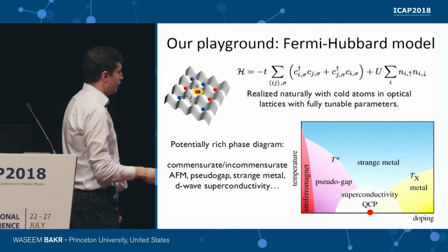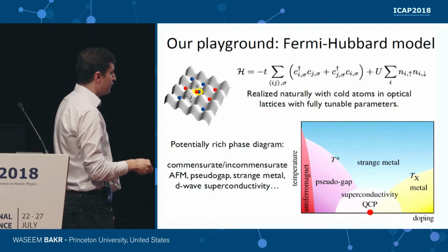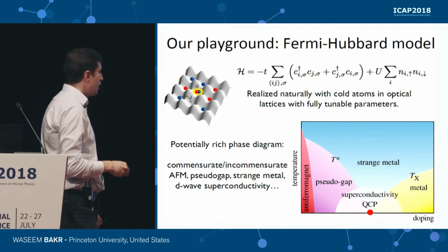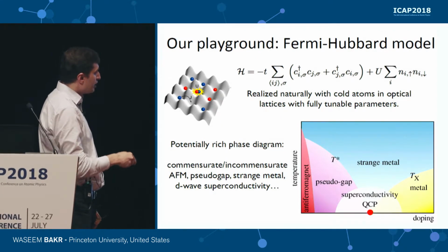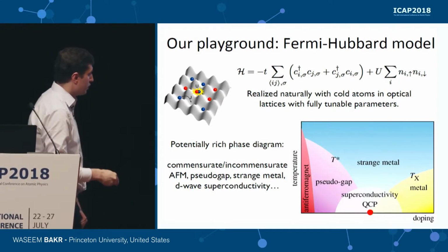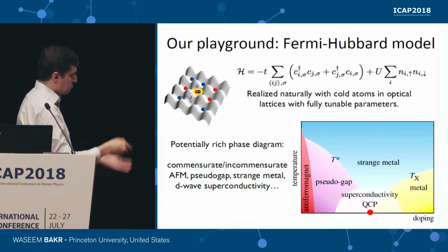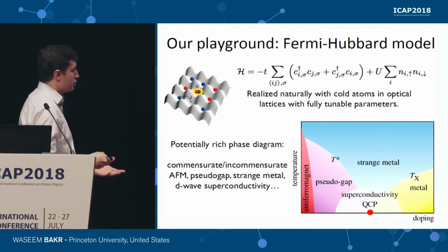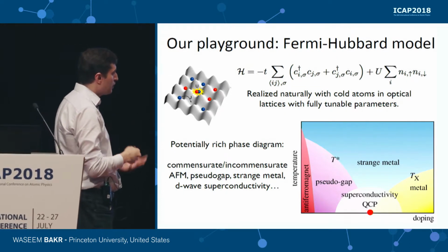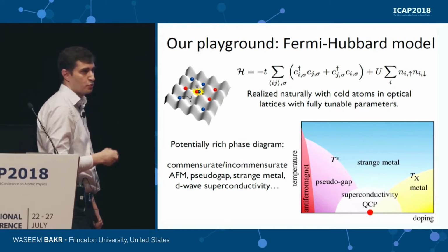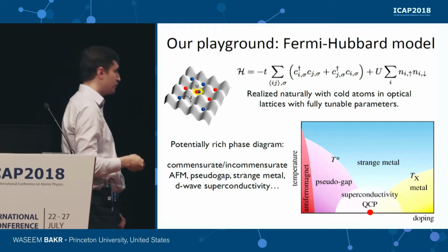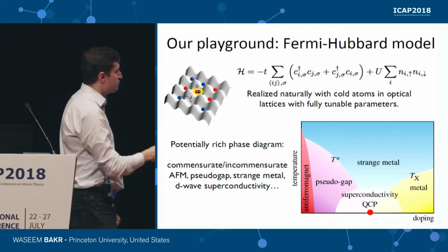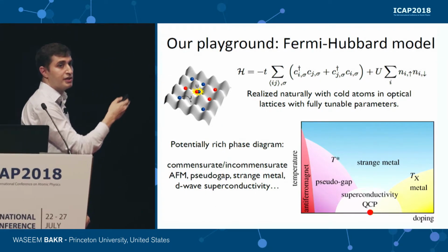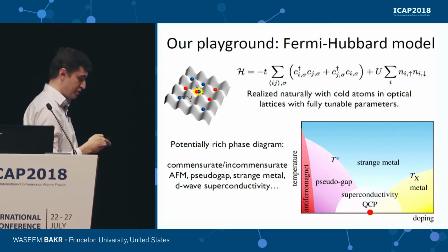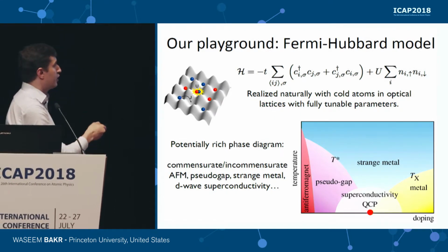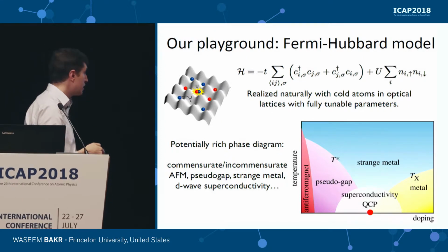So there's a lot of effort trying to reach low temperature equilibrium phases, like, say, pseudo-gap phases. But there are actually high temperature phases, like the strange metal at finite doping and relatively high temperatures, which are not described by equilibrium quantities. They're described by transport properties, which one might hope to see first. For example, in the strange metal phase, like the bad metals, there's a linear in temperature resistivity. So we thought, okay, let's see if the Hubbard model can see some of this phenomenology.